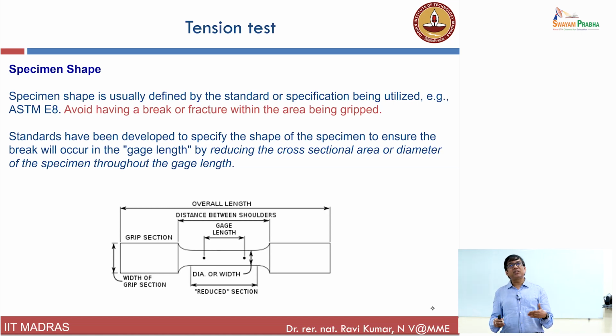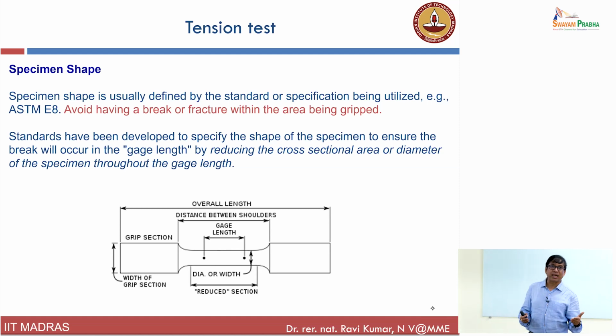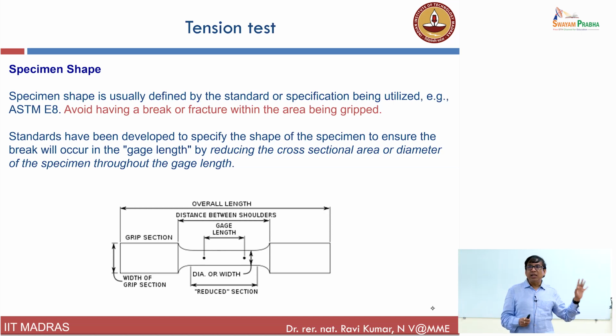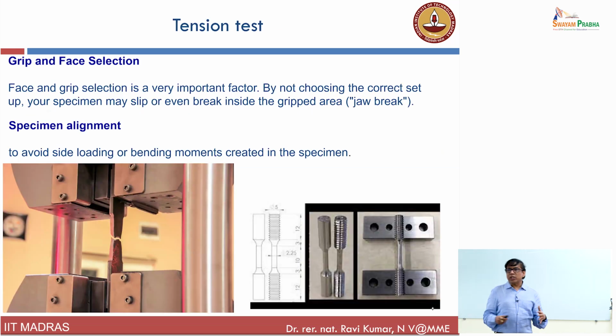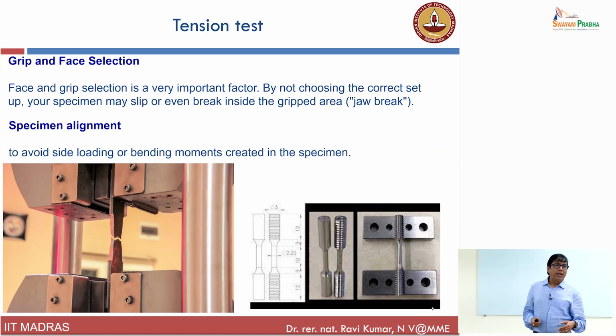For example, in ceramic samples, it's very difficult to always follow ASTM standards. Then you have to do a large number of tests to validate it. Otherwise, people will not accept your data. In metallic materials, it may be easy and it is well established. In ceramic samples, it's not always well established. You may not have ASTM standards to follow. And when you do not have them, you have to perform lots of tests, validate the data, and confirm to people and the community that you have actually generated a lot of data, and therefore the data is reliable. And other issues are mostly how to handle it. For example, this is again something that I have noticed more in India.